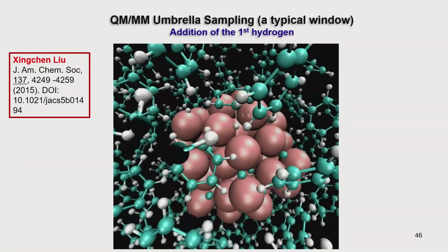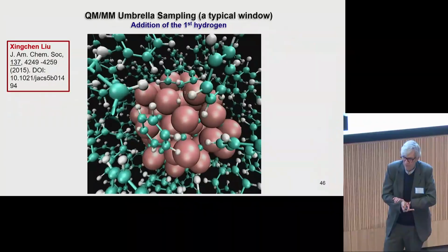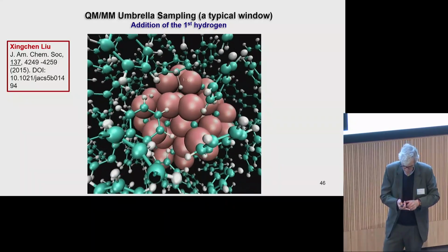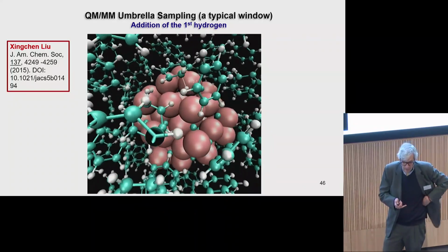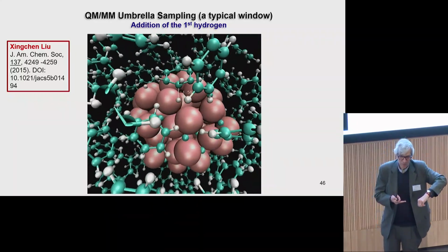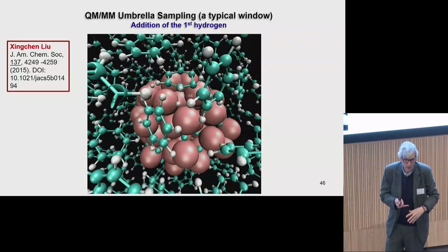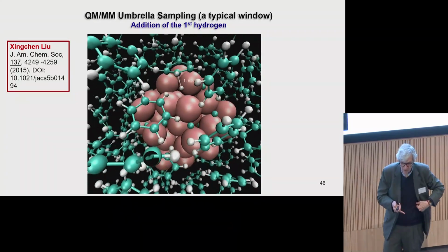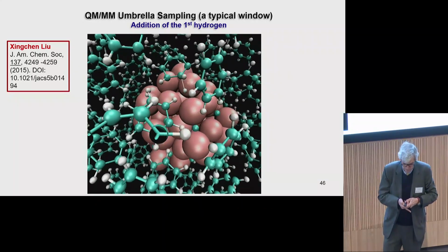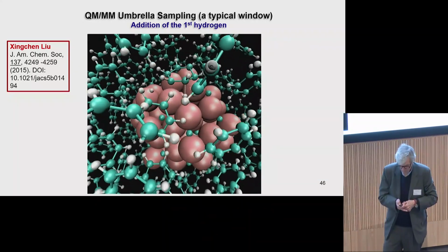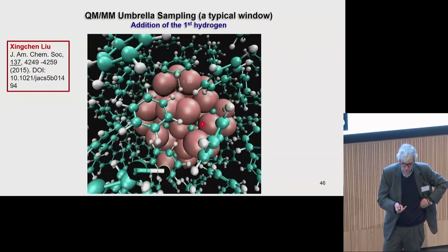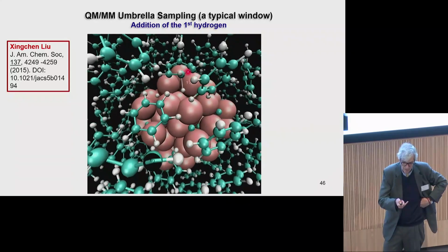This is still one of my favorite movies, just because I found it so surprising that there was such a lot of movement in the molybdenum carbide nanoparticle. Coming from a background of surface chemistry, I naively thought molybdenum carbide is hard and it's not going to move very much. But that's certainly not the case at 400 Celsius. And the entropic part of the free energy diagrams are hugely important for this kind of system. Indeed, it even looks like general ideas like a particular reactive site.